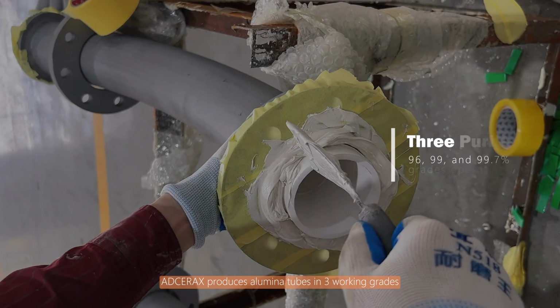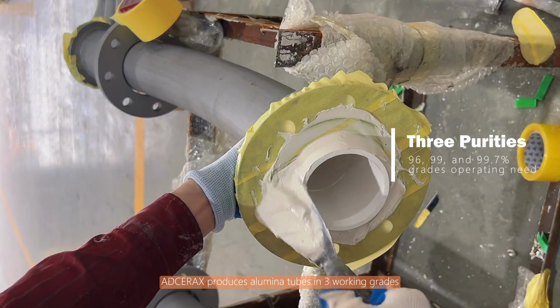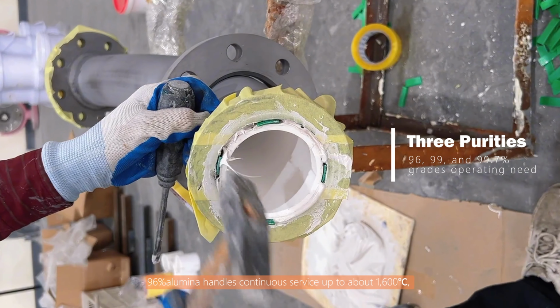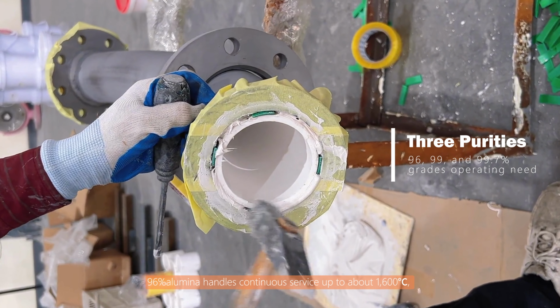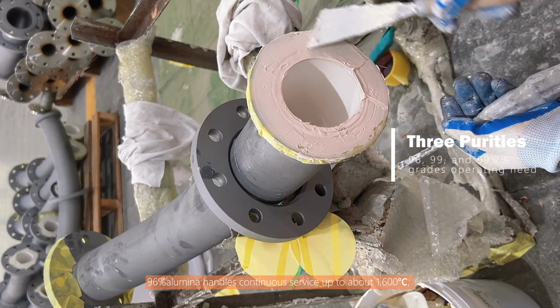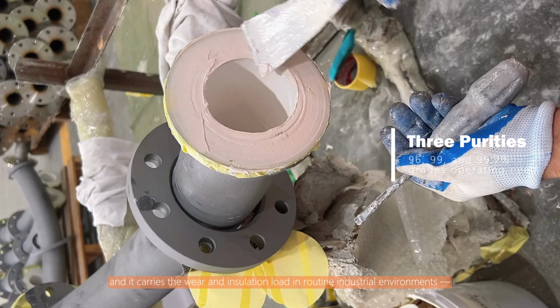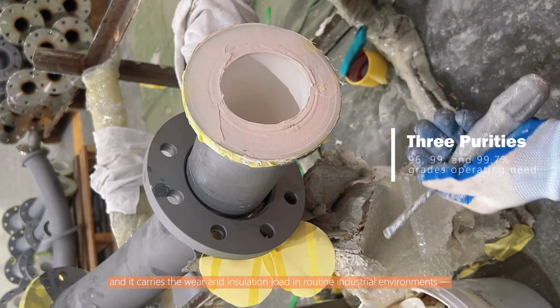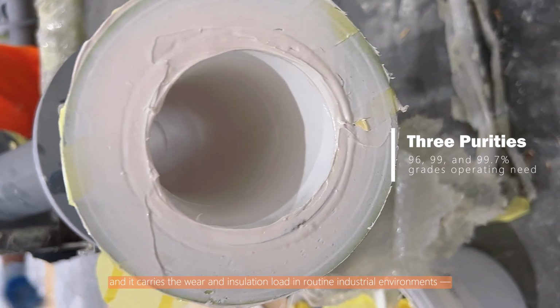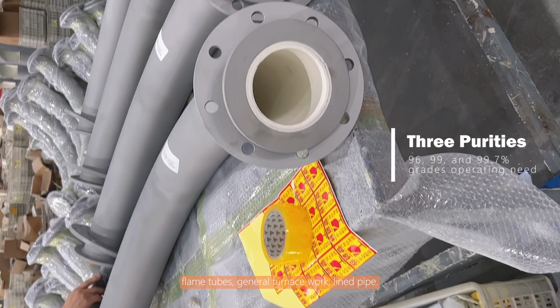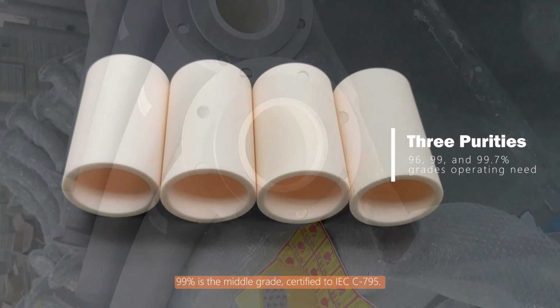ADCERAX produces alumina tubes in 3 working grades. 96% alumina handles continuous service up to about 1,600 degrees Celsius, and it carries the wear and insulation load in routine industrial environments: flame tubes, general furnace work, lined pipe.